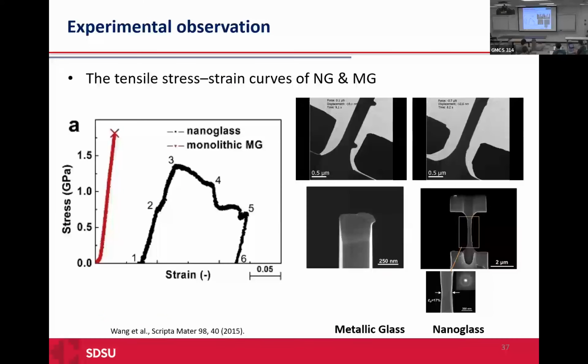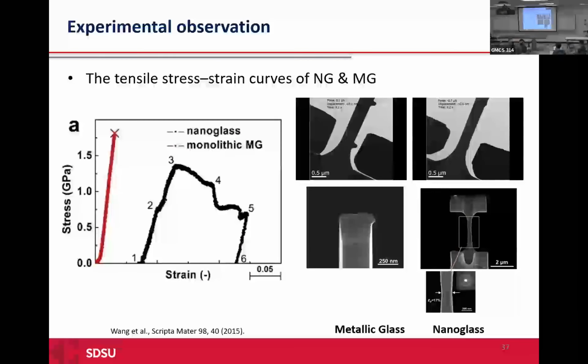Then we also had a collaborator in Germany who did some of the experimental work, and we could see that from the experimental results as well. For the metallic glass sample, it breaks through a shear band, and for the nanoglass there is some necking, and you can see that the strain it can tolerate increases under the nanoglass samples.